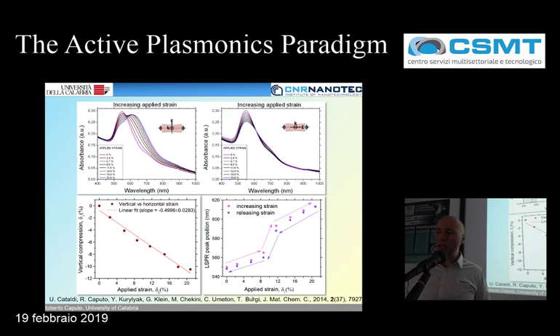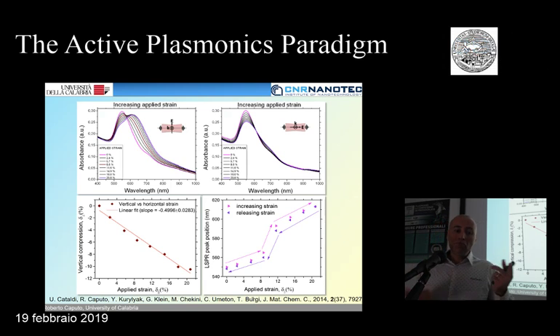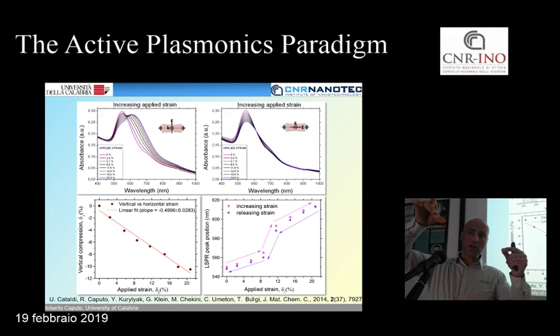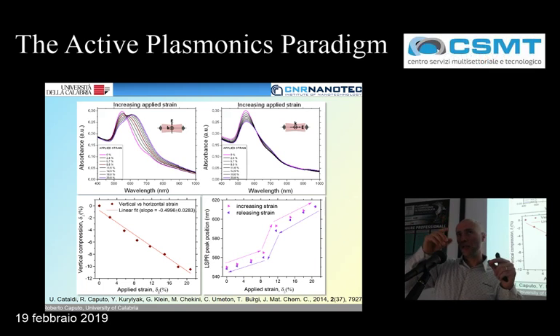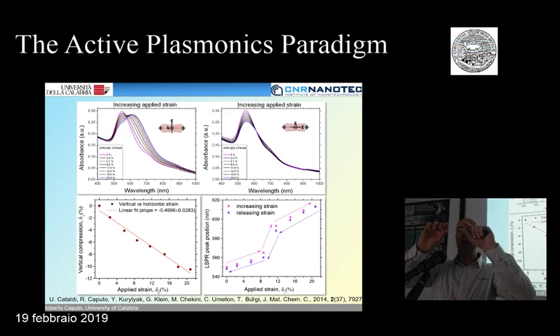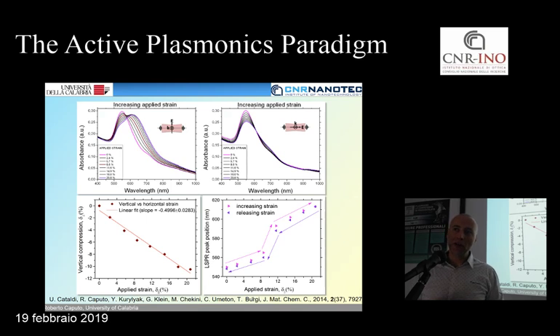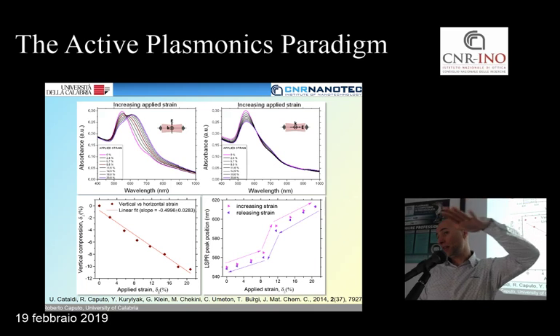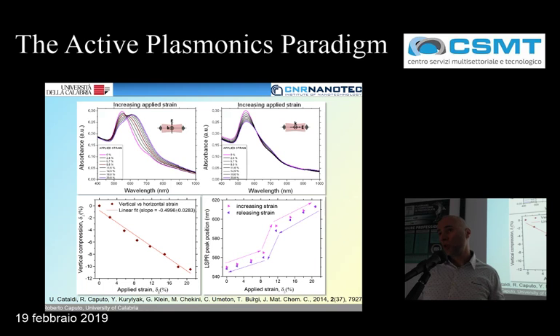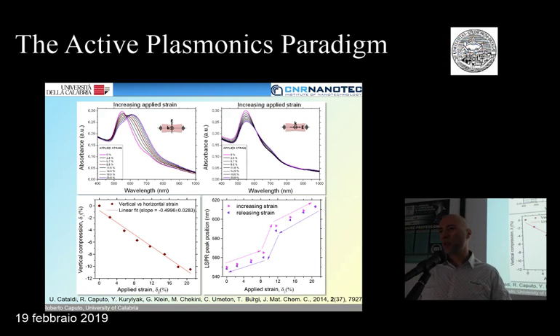For what concerns the question, we have three possible directions. One is the elongation in plane. Another direction is the compression. And you should even consider a third one, which is the thinning of the substrate, because you could say Y, X, and Z. So along Z, we should have our substrate thinner during the stretching action. But I think this should not affect the behavior of the system very much, because the particles are on a plane, on the surface of the sample. So we just considered the main two directions, the elongation and the perpendicular, because they are the most influential ones, I think.